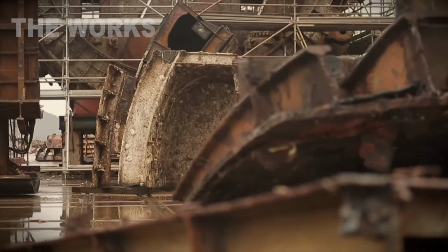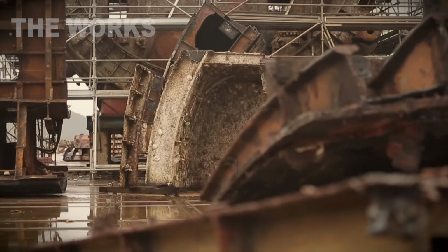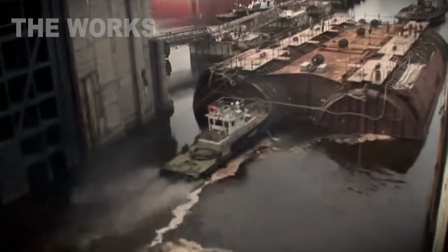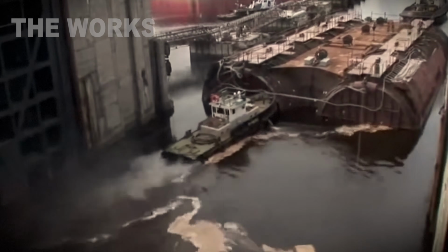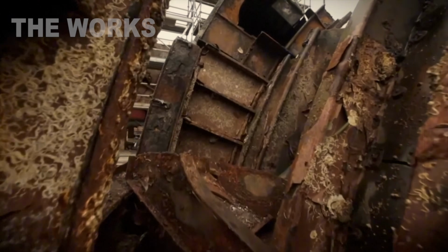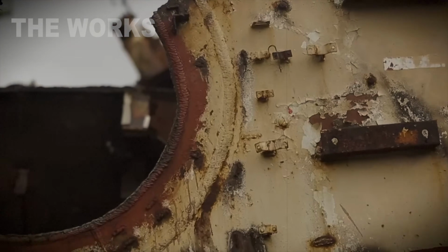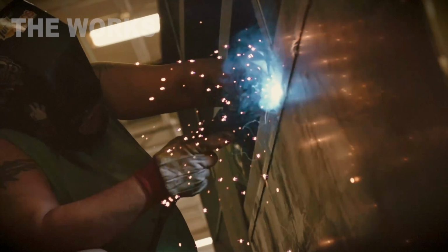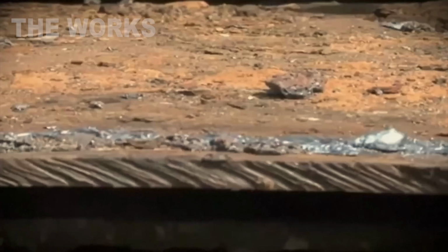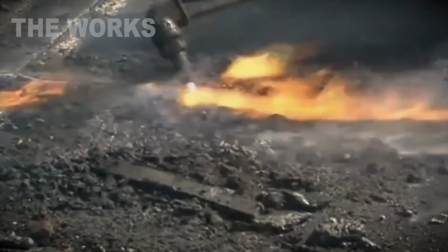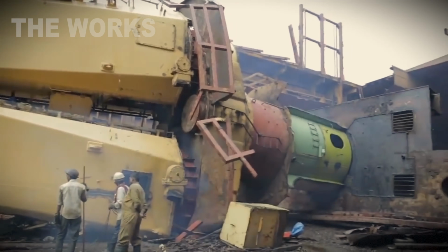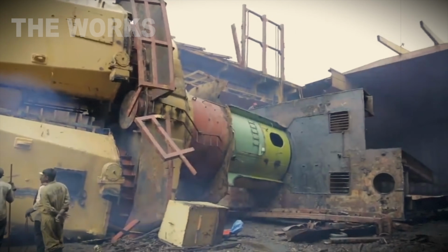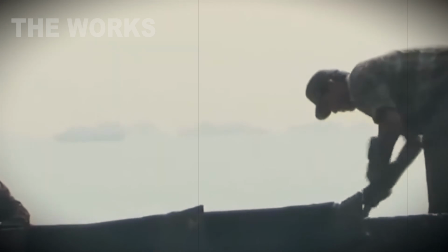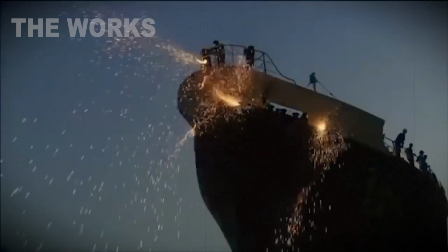The lance burns clean through the steel, leaves a molten seam 2 inches wide, burn through speed, 20 inches per minute, faster than plasma. But it takes serious skill. You guide the lance dead perpendicular, deviate more than 10 degrees and the burn's incomplete. Crews of 4. Protective suits made of Kevlar, masks with number 13 filters. They block infrared and ultraviolet radiation. Without the mask, your retina burns in 1 second.